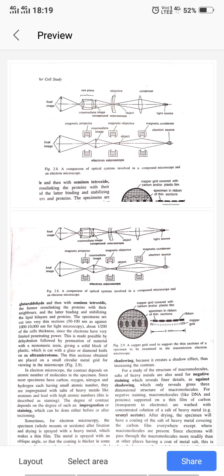Sometimes for electron microscopy, the specimen after fixation and drying is sprayed with the heavy metal, which makes a thin film. The metal is sprayed at an oblique angle so that the coating is thicker in some regions than in others. The process is called shadowing because it creates a shadow effect, thus increasing the contrast.